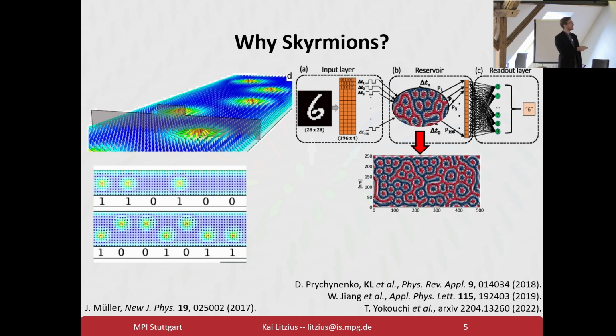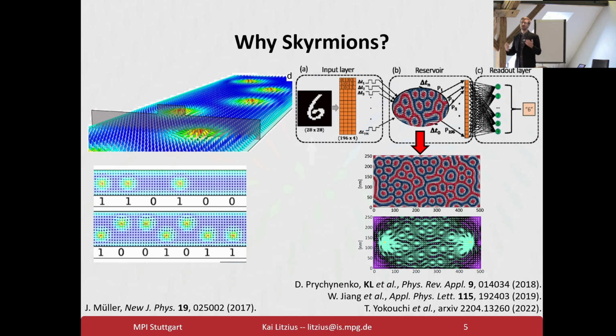Our proposal for that was done by Karin's group while she was still in Mainz, Karin Everschor-Sitte's group. It was to use a reservoir of skyrmions and domain walls in a dilute array, where you have a contact here, a contact there, and then you pass current through it. Then something happens that looks a bit like shifting rocks in the side of a riverbed. Let's say you have very strong input, which corresponds to very strong neural activity. Then you start shifting around the magnetic textures, and you create a path of low resistance. By creating a path of low resistance, you can afterwards read that out and detect that this path has low resistance. There must be an active connection.